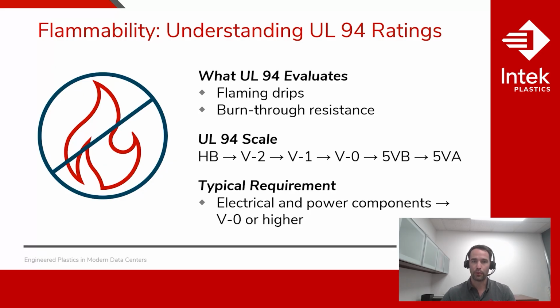UL 94 evaluates the burning behavior of a material, and it looks at three primary criteria, those being how quickly or whether a material self-extinguishes, whether it produces flaming drips that ignite a cotton ball positioned below the test specimen, or whether the flame can burn through a material from one surface to another. So starting at the lowest end of the burn performance scale is HB, or horizontal burn. As the name suggests, your specimen is oriented horizontally and a flame is applied, and the test evaluates how quickly or whether the flame is able to burn horizontally across the test specimen.